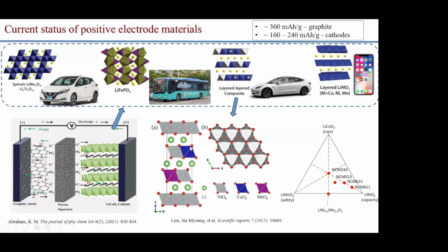But in the near term, they're going to remove most of the cobalt and make it high nickel content, so you get high energy density. The problem they're working on is how not to compromise on safety, because nobody wants to compromise on safety. As you push to higher nickel with less cobalt, you compromise on safety. So that is something they're working on now: pushing to higher nickel, NCM 811 or NCA, but still retaining some of the safety.